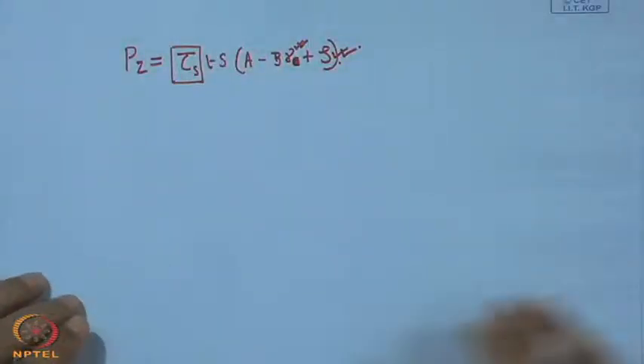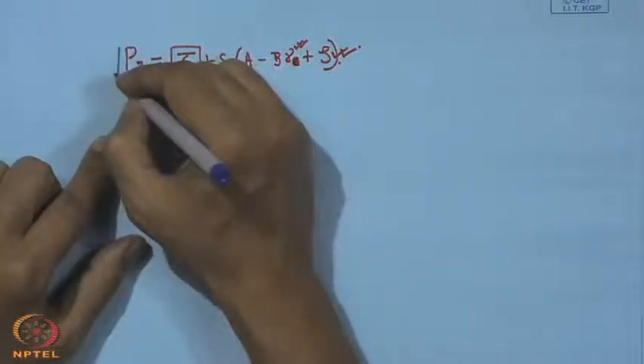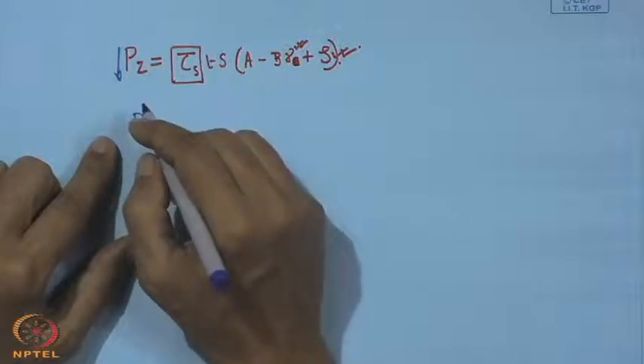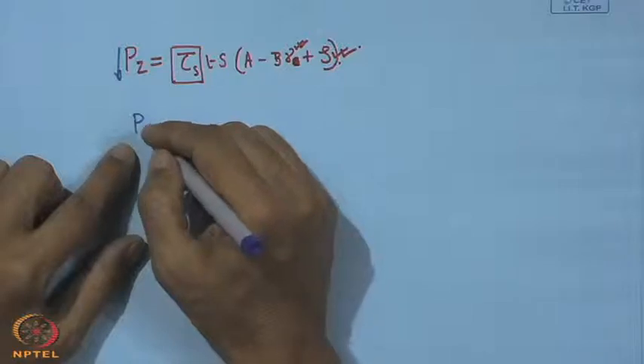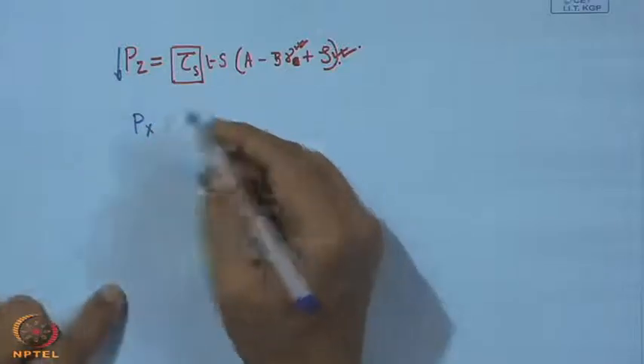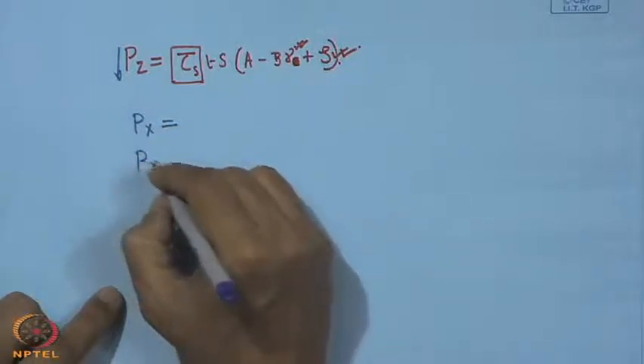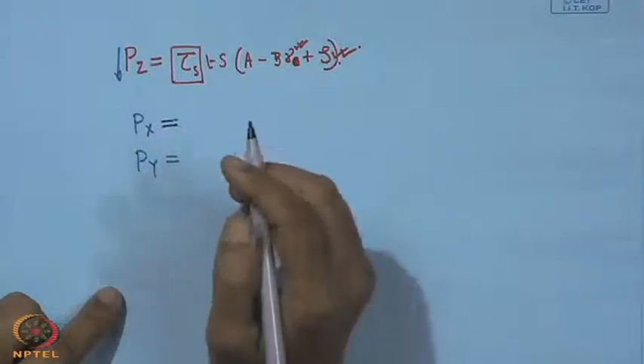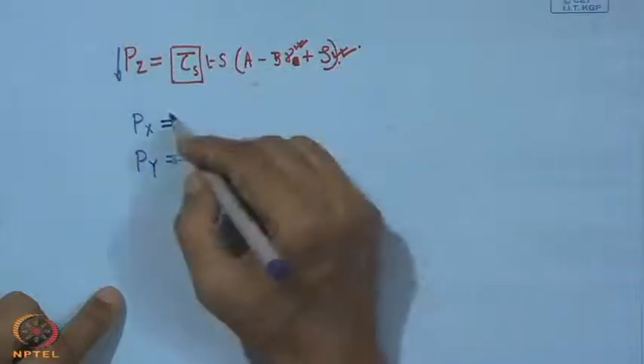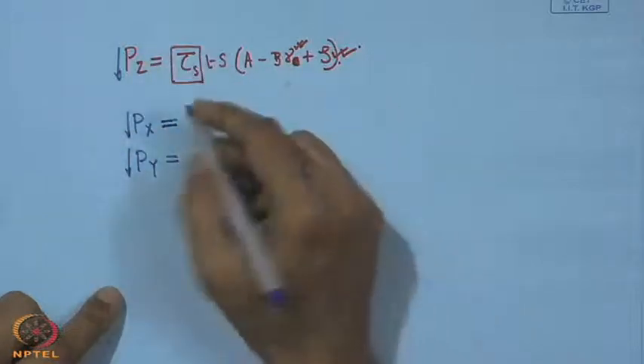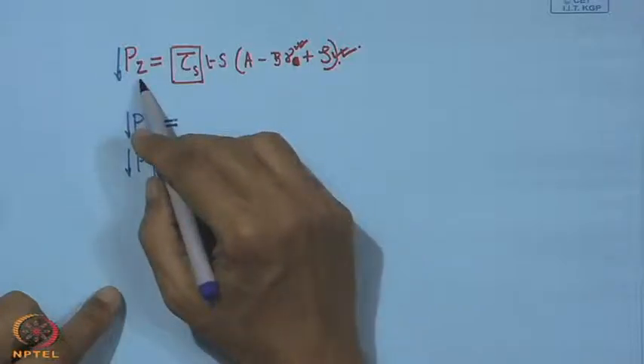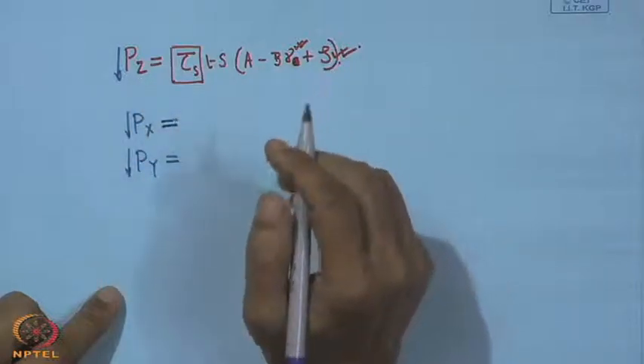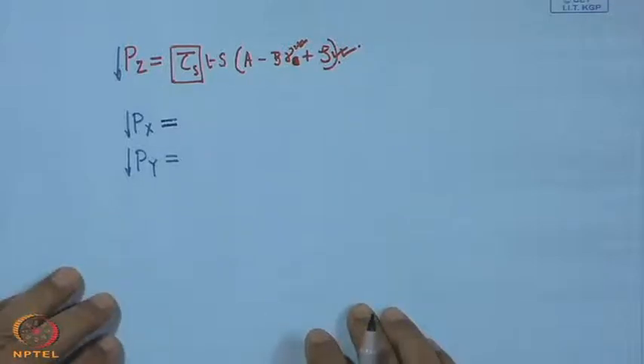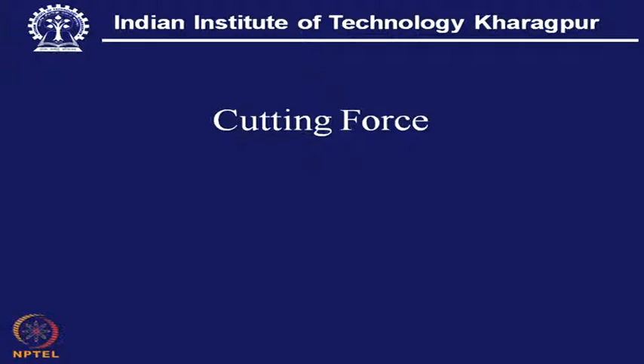So, it is a twofold advantage, that means the P z value can be brought down, then P x, which is the axial force, but this axial force is very close to the friction force which is prevailing at the chip tool interface. So, this P x, and then we have a value P y, but what is important, this P x value can be reduced, but since P z is reduced, then overall P x will also be reduced, P y will also be reduced, because they are interactive, and this P z value can be reduced by this reduction of zeta. So, measurement of the cutting force also appears to be one of the important steps in determining the capability of the TiN coating.